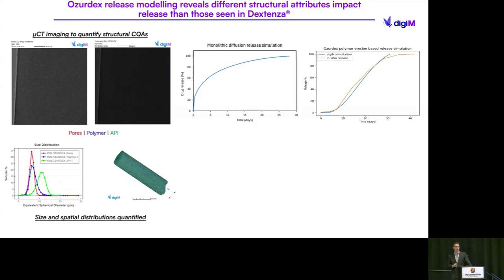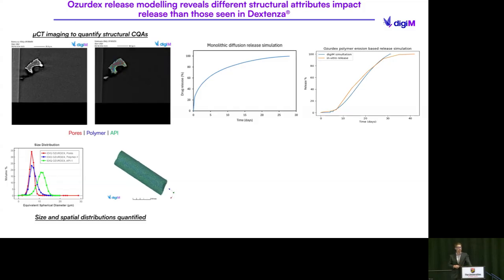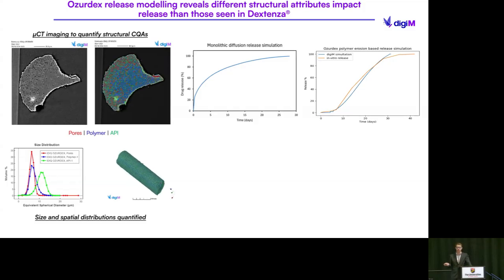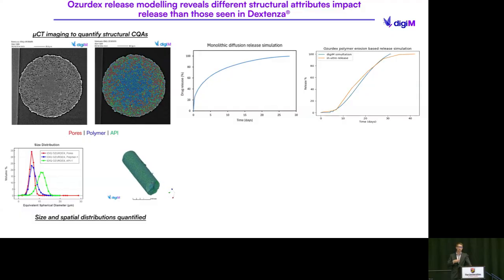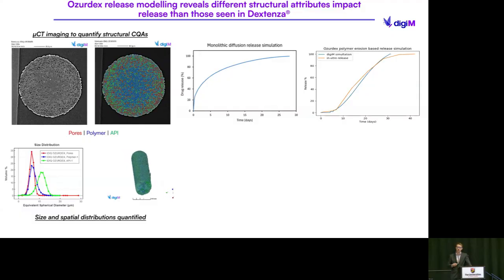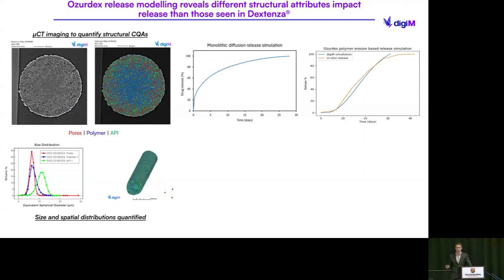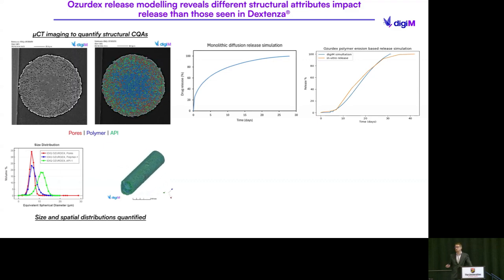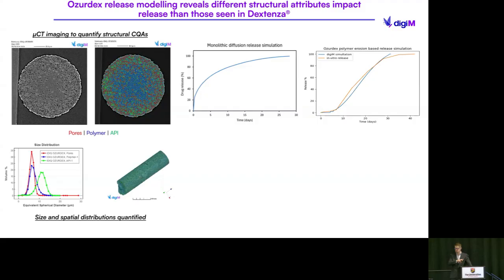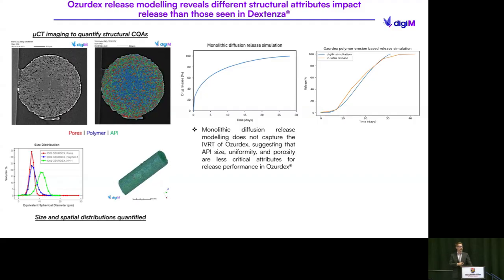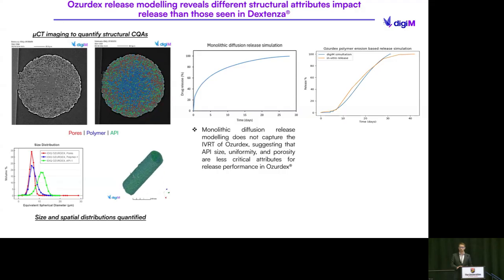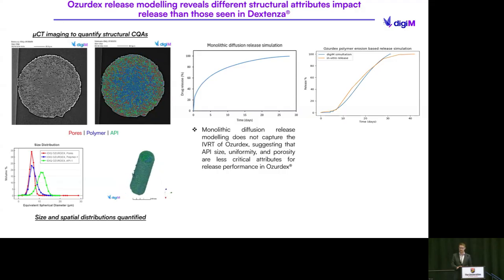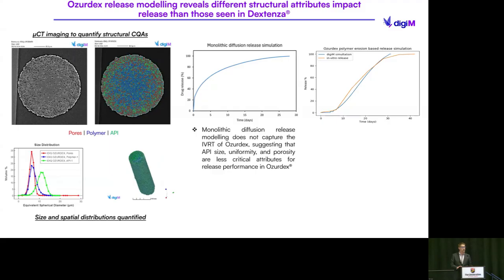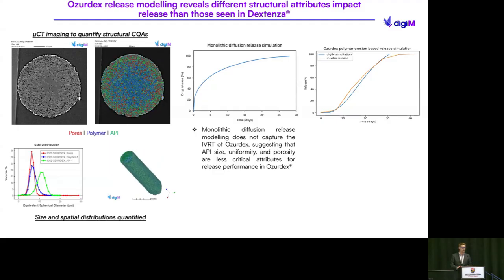And so I'm showing 2 here now, because on the left, we did a monolithic diffusion simulation here, which is an excellent and easy starting point because there are nice closed-form analytical solutions for that. And most people have heard of Higuchi, and nobody argues about what's going on there. The challenge is that the release curve looks nothing like what compendial in vitro release methods look like, what it looked like in the product listing.